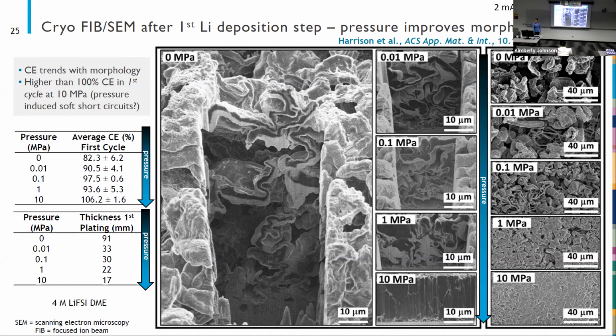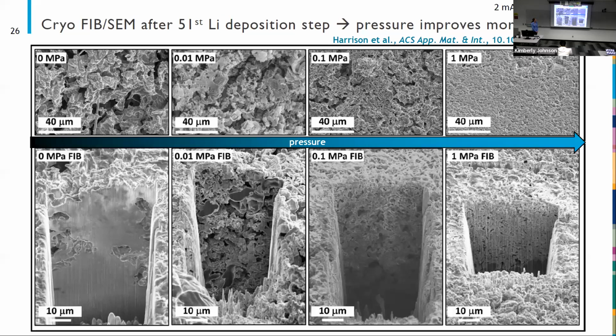So clearly the pressure has a huge impact on morphology at the current that we're looking at here. We next looked at cryogenic FIB and SEM at the 51st cycle, and we wanted to see if the pressure only mattered in the beginning or if it continued to matter throughout cycling. And you can see that the morphology continues to be denser and better controlled at higher pressure, even as we go to these longer cycle lengths.